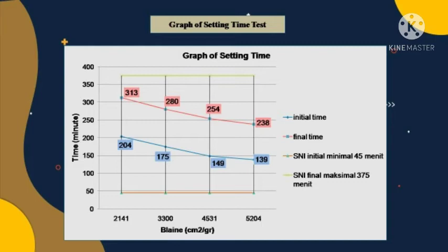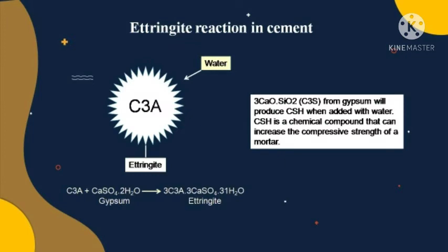There are two lines with different colors. The first line is blue, showing the result of the initial time, while the red line shows the final time. Both lines show a graph decreasing from the lowest value to the highest Blaine value. This explains that the higher the Blaine value, the faster the time it takes for cement to bind with water. As previously explained, the finer the cement particles, the faster the cement hydrates with the water.